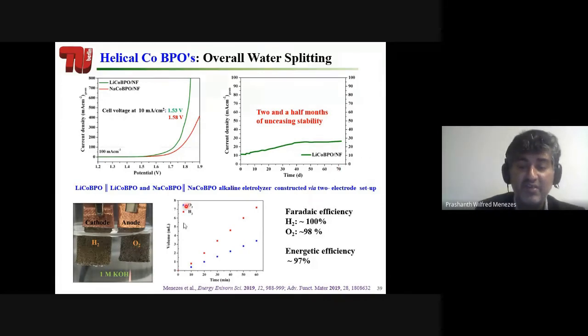And also, this is something called Faraday efficiency, which I told you in the beginning of the slide. That means how much charge we pass, how much current we get. Our efficiency is almost 100%. We can produce 100% of hydrogen and almost 98% of oxygen in the system. And the overall energetic efficiency we reach is about 97%.